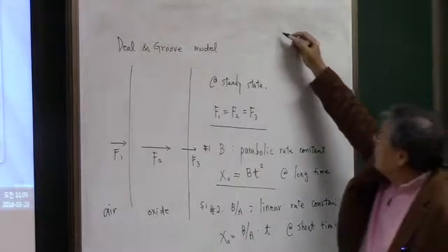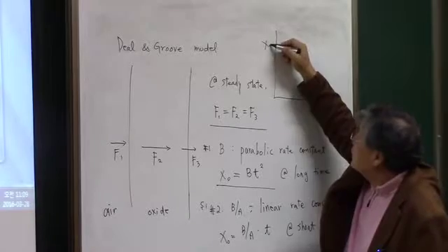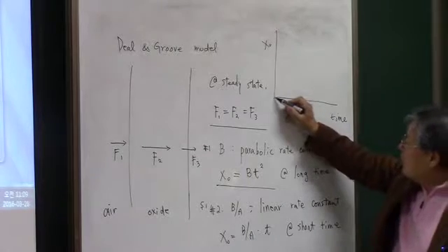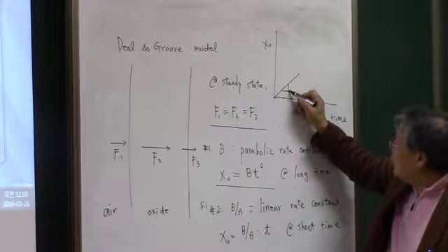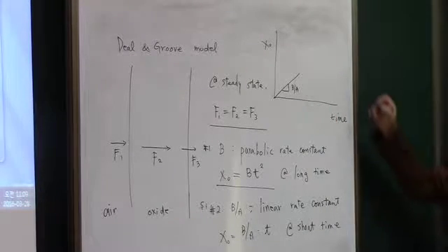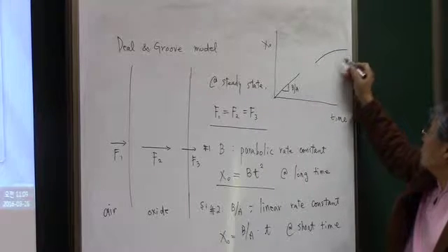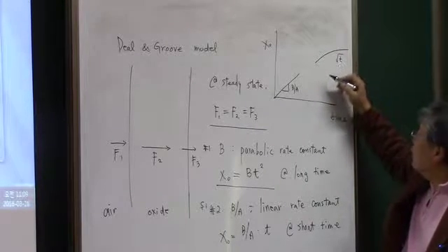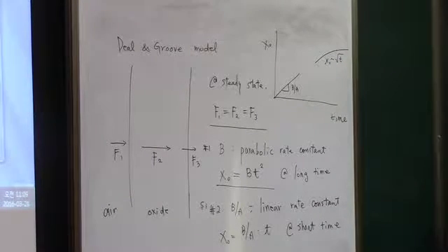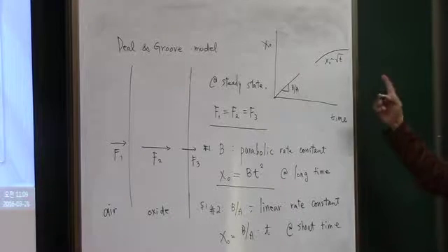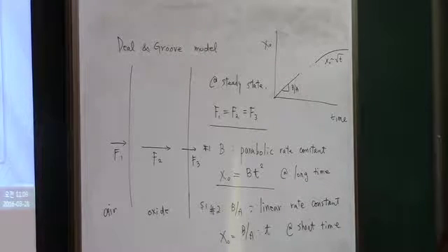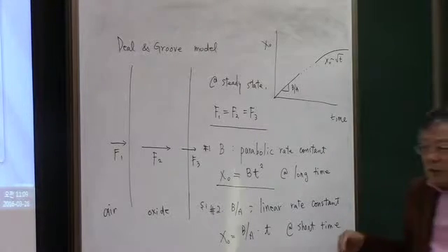So basically what we are saying here is that at the first stage of the oxidation, the oxide thickness is a straight line related to B over A, and later it goes as the square root of t, so the oxide thickness is proportional to the square root of t. Okay, we have somewhere in the middle. So that's the conclusion that we discussed the last time.